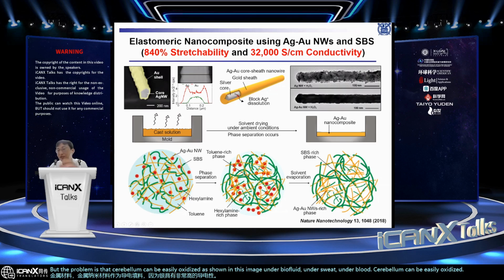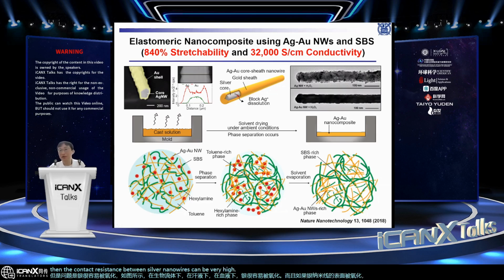And if the surface of the silver nanowire is oxidized, then the contact resistance between silver nanowires can be very high. So although the silver nanowire itself has very low resistance, due to the high contact resistance, the overall percolation network will have high resistance. That's the problem. Another problem is that inside the biofluid, silver nanowire can be dissolved. So silver ions can be leached out. And silver ions are toxic. So that is a problem. There is a problem in biocompatibility.